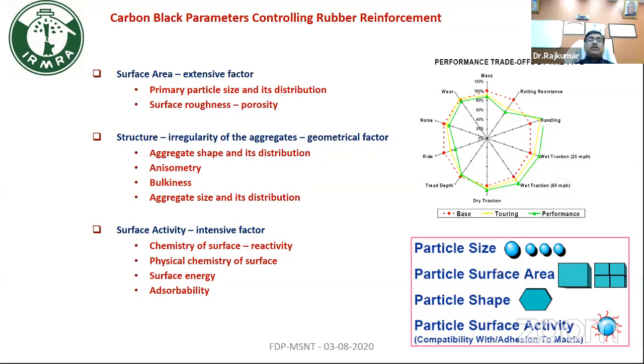So how the primary particle size, its distribution, the surface roughness and porosity, structure, irregularity of the aggregates, geometrical factor, aggregate shape, anisometry, bulkiness, aggregate size and distributions. So these are the carbon black factors that were limiting the technological advancement in carbon black. Now the surface chemistry, surface activity takes over, especially in nanotechnologies.